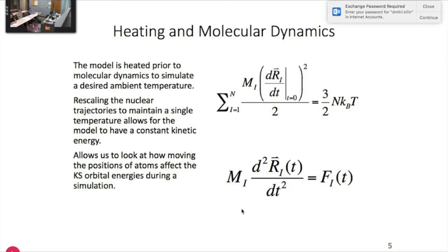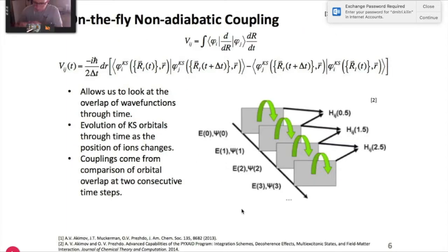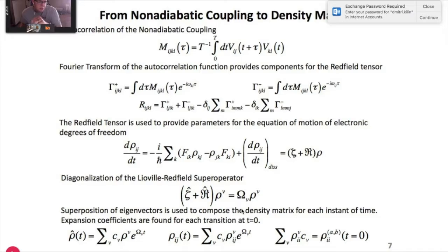the dynamics. And then going through the dynamics, being able to look at the electronic structure as a function of the atomic positions and how it changes from time step to time step to try and account for the atomic motion, and what role it plays in migrating photoexcited charges within the material. And so once we have these non-adiabatic couplings determined between the time steps, we put them into a Redfield tensor which provides the transition probabilities between individual states, which is one portion of the overall equation for motion of electronic degrees of freedom. And so the Redfield portion coupled with the Liouville can allow us to study this time-dependent density matrix.